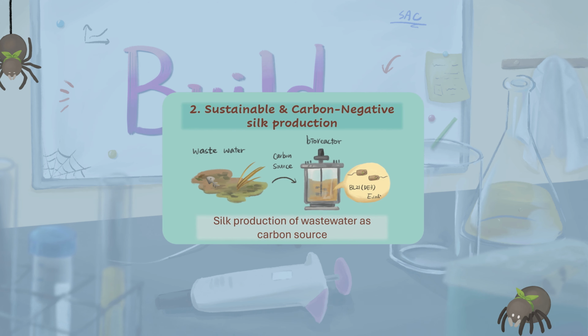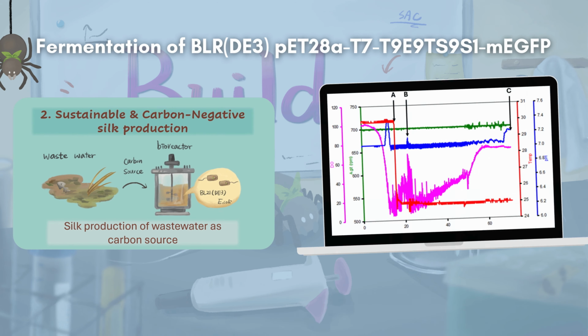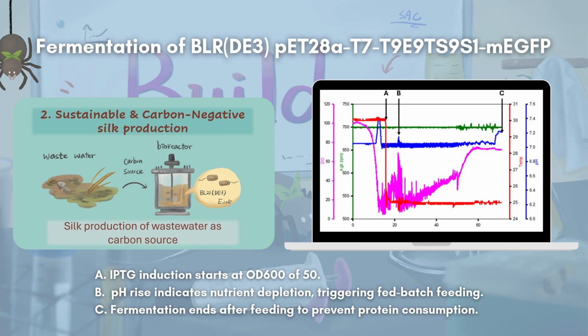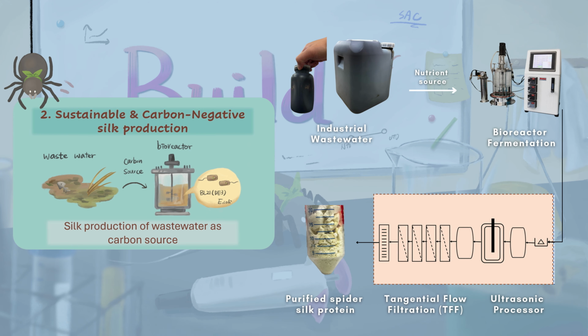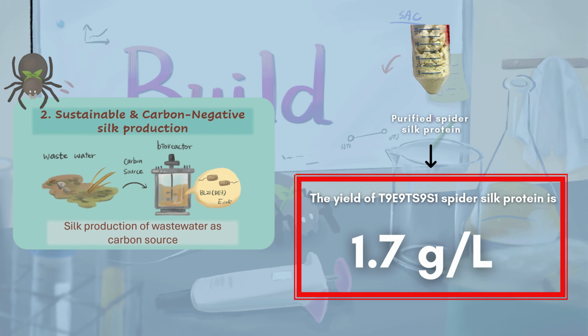For deeper insights, we observed the formation of T9E9TS9S1 spider silk micelles using fluorescence microscopy. After confirming the protein's accuracy, we immediately began the fermentation process using wastewater. Once fermentation in the bioreactor was complete and the pH became alkaline, indicating nutrient depletion, we harvested and lysed the cells. This released the spider silk proteins, which were then purified and treated with SDS. After centrifugation and washing with deionized water, we achieved a final yield of 1.7 g/L, marking a significant milestone toward